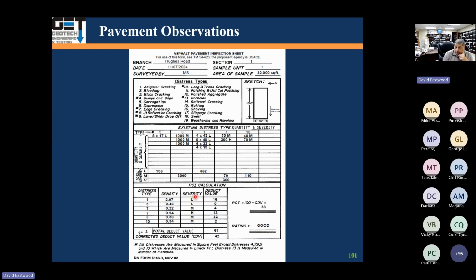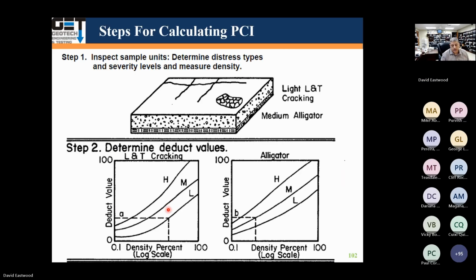So basically, you go through the density on these things. Once you get the density at each one of these, you go through what's called a deduct value. You go through the density, you go through these curves, depending on low severity, medium severity, and high severity. This is for longitudinal and transverse cracking. This is low density, you get a deduct value. Again, for alligator cracking, you get the density, you go to these curves, it's a medium severity, you get a deduct value.